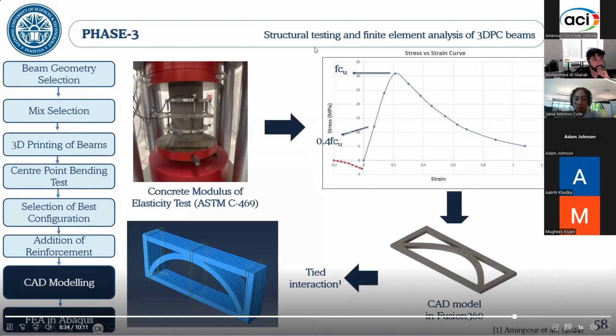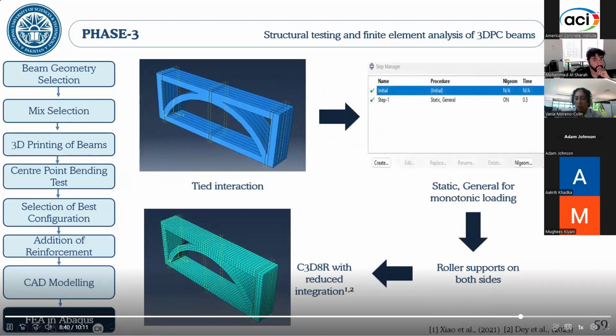For the numerical analysis, we modeled the arch infill beam in Fusion 360 and imported it in Abaqus. We used the to simulate our tests. We used a tied interaction between the layers, used static general for monotonic loading. We used roller supports on both sides to mimic the real-life experimental conditions, and used an 8-node linear brick element for the meshing.